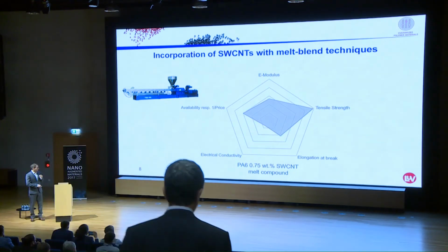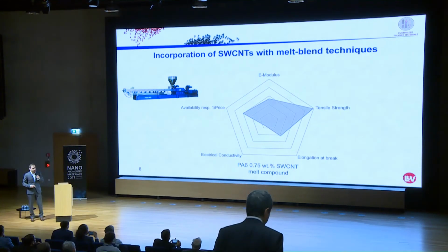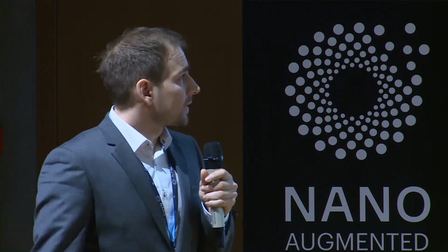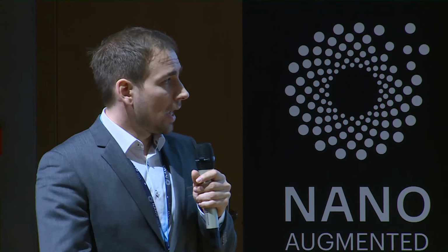And we also see that the electrical conductivity is increasing really slowly. And just at 1% incorporation, we break through the percolation threshold and achieve a really nice electrical conductivity, a high E modulus, high tensile strength, but we have two weak spots here in this diagram. It's the availability and the elongation at break. And this was my task, to find a solution here.